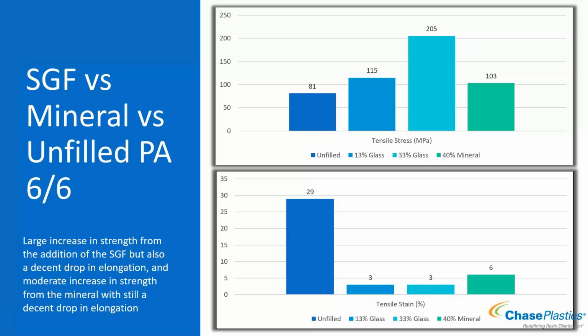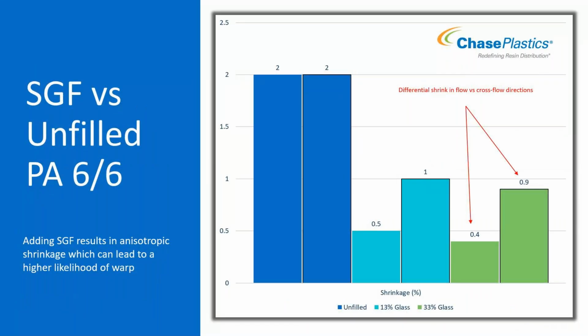And then your shrinkage, again back to short glass versus unfilled. If it's an unfilled product, shrinkage is at 2%, or 20 thou inch per inch, but flow and cross flow are at 2%. So if flow and cross flow are the same or just about the same, that's uniform shrink, isotropic shrink with it being unfilled. Then you move to the 13 glass and the 33 glass.